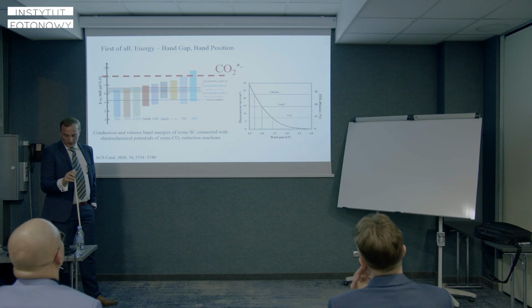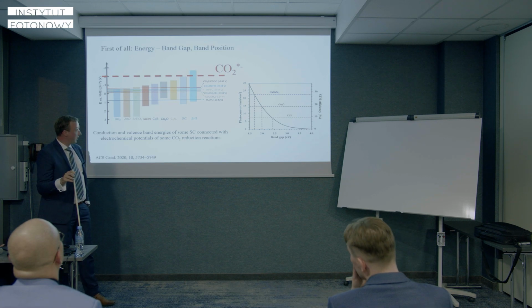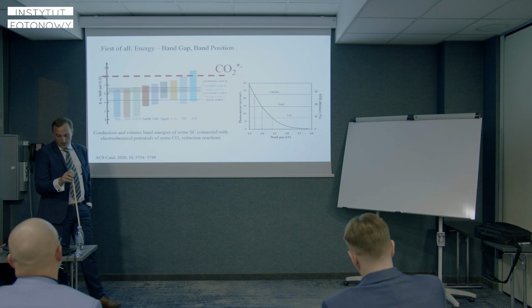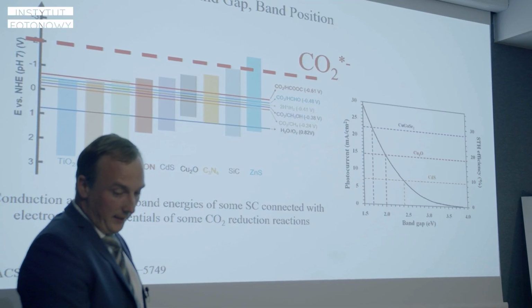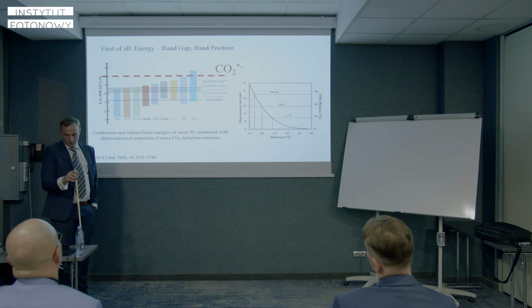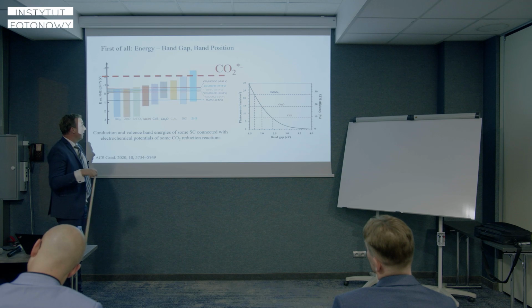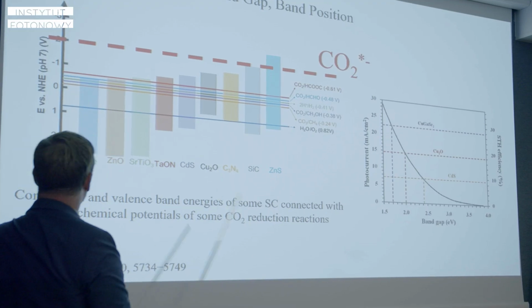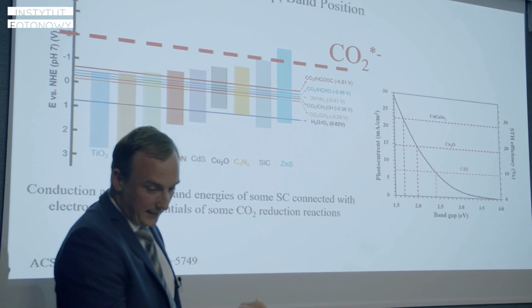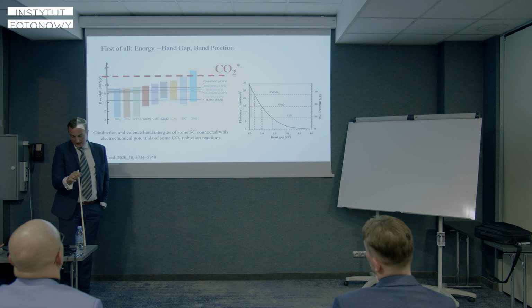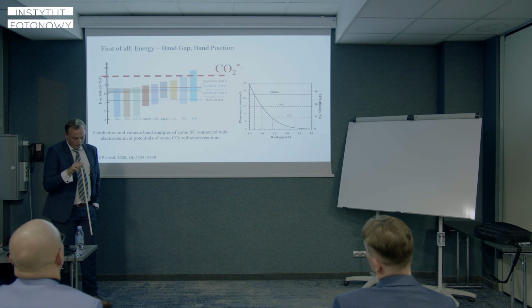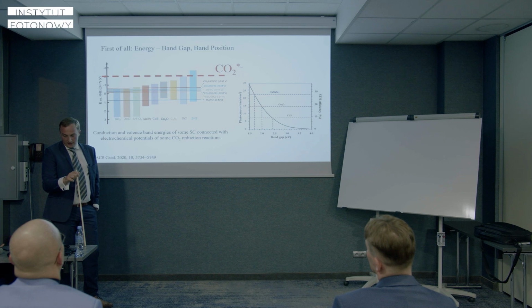Generally, it has been reported that one-electron reduction of carbon dioxide involves the formation of a carbon radical intermediate during the first step of the reaction. However, the creation of the carbon radical needs almost -2 volts versus the hydrogen electrode, and it's completely thermodynamically disfavored and systematically considered as the rate-limiting step for the whole reaction.